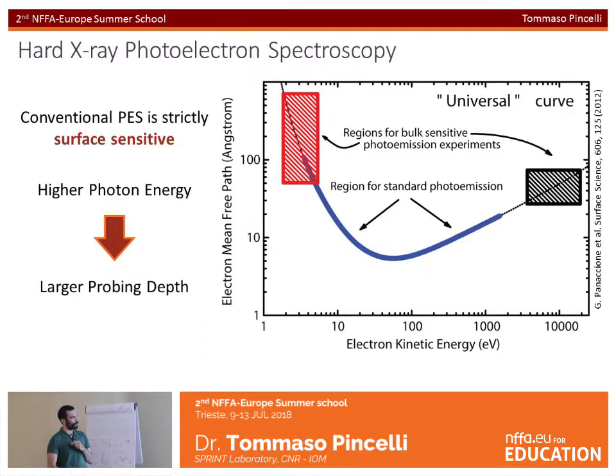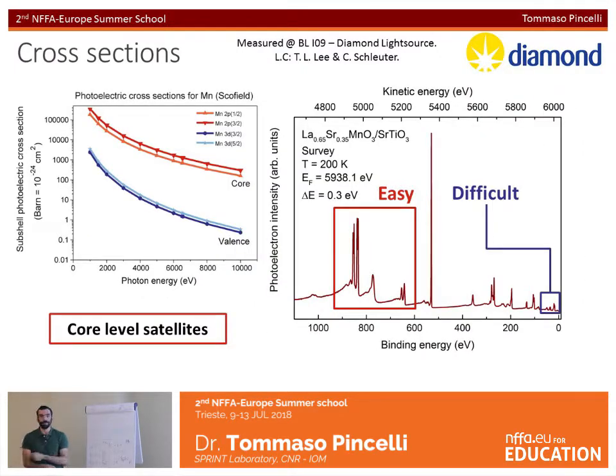This comes at a price, though, because the photoelectric cross-section decreases significantly as you increase the photon energy, and therefore you become less and less able to measure clearly, and you have less and less statistics, basically. And this decreases particularly fast for the valence electrons that are the ones that we want to look at. So we need to find a fingerprint of how the electrons are mobile through the crystal by looking at the core levels, which are easier to measure. And luckily, this is possible.